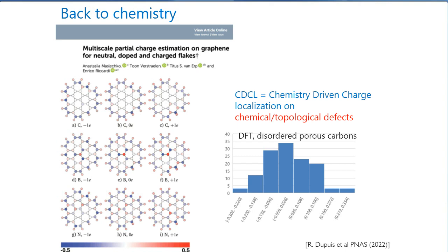We did a bit of DFT calculation of our porous carbon. The main bar corresponds to carbon atoms with almost zero charge, and you see with the defects some atoms in the tail of the distribution that are non-zero — those correspond to the non-sp2 carbons. The central bars correspond to the sp2 carbons. The electrode thickness is about two nanometers, so because of the two outside surfaces, 70% of the atoms are sp2 carbons and 30% are defective — either inside the electrode or on the outside surface.